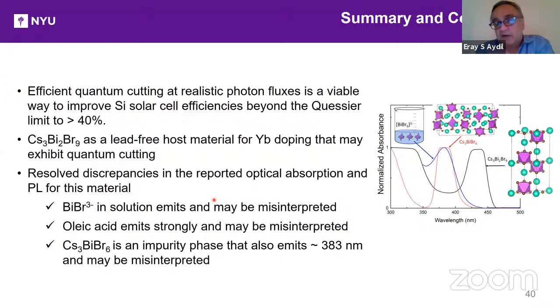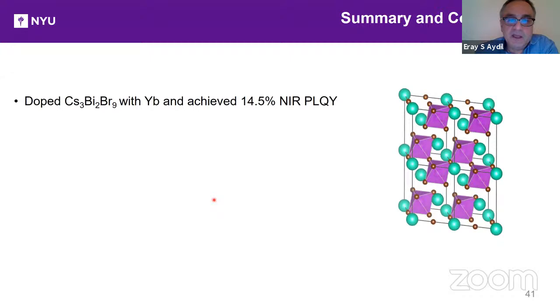And we're confident that the absorption and photoluminescence that we are reporting for the PVD films are for the Cs3Bi2Br9. Incidentally, all of that agrees with single crystals, which is work that was done way back in the 1980s. We doped this material with ytterbium and achieved 14.5% near-infrared PLQY, and that's the highest of these lead-free materials in terms of photoluminescence quantum yield. We think that the ytterbium, at least some of it, substitutes into the bismuth positions.